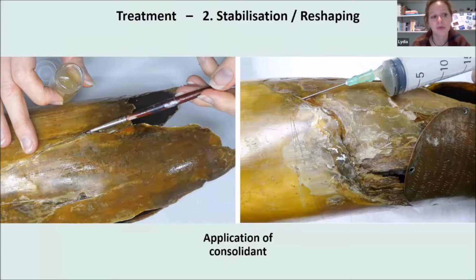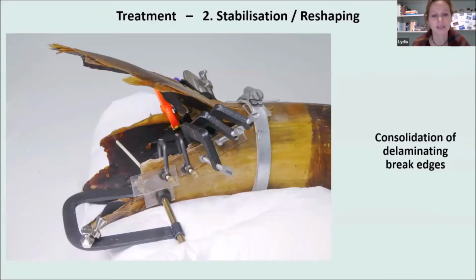A weaker protein glue would have failed halfway through the procedure, and even with bone glue, it was sometimes a balancing act to keep the bond stable. I applied the adhesive with a brush or a syringe between the laminating layers. The drying process could take up to 12 hours, and during that time, the layers had to be pressed tightly together and into the right position. This required different techniques in different areas, and I had to be inventive to apply the pressure I needed. Along the break edges, I could apply clamps to press the delaminating layers together while the adhesive was drying overnight.